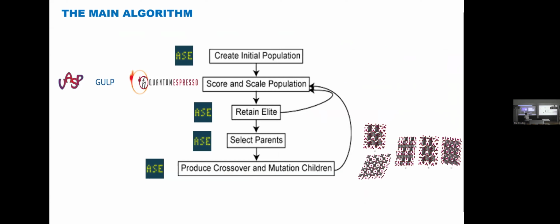I want to apply neural networks here. We create the structures using Python. We have made this code to create the structures, but then in some way we had to calculate the energy of the structures. We used GULP, Coulomb potentials, to calculate it, but it's not good enough because it doesn't include some quantum effects like spins. At this point, it is reasonable to change GULP or DFT methods to machine learning.